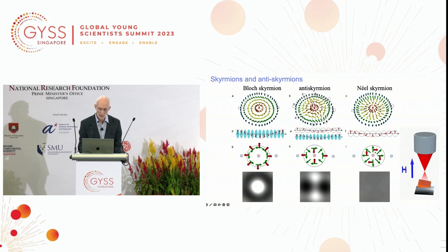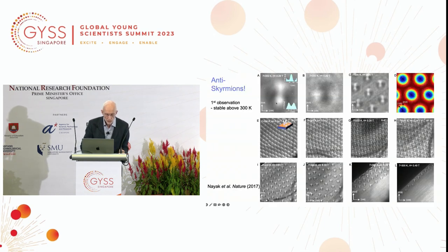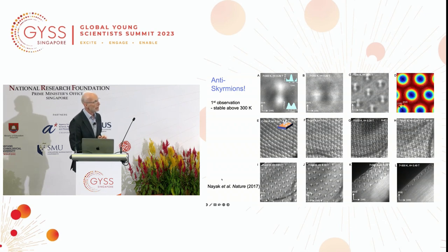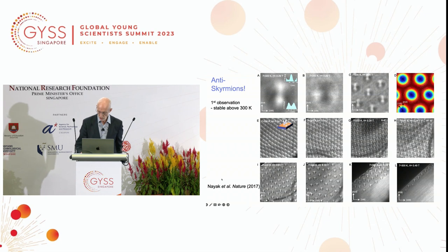And a Néel skyrmion, actually, if you image it, you'll see nothing, but for a Bloch skyrmion, you'll see the electron beam is focused towards the middle of that skyrmion, it would look like this, and we predicted that an antiskyrmion would show, as the electron beam was transmitted, two regions of high intensity, white, two regions of low intensity, black. And I think you can see, here is the image we saw. This is an antiskyrmion. The first observation, it's about 200 nanometers in size, and we published this 5 years ago, and we showed that as a function of magnetic field and temperature, we could evolve these structures into more complex